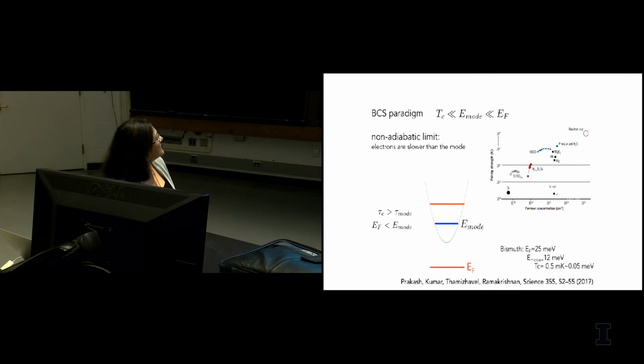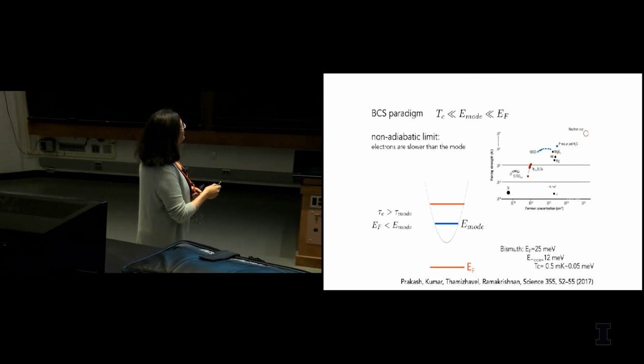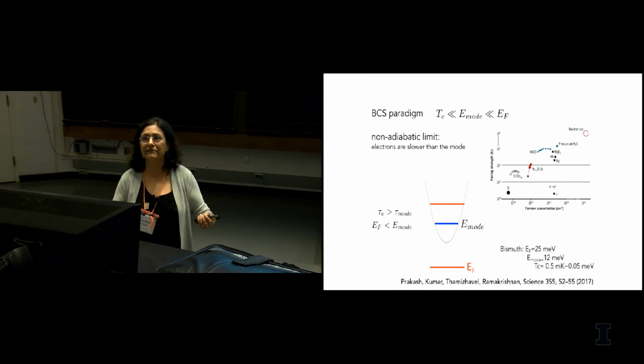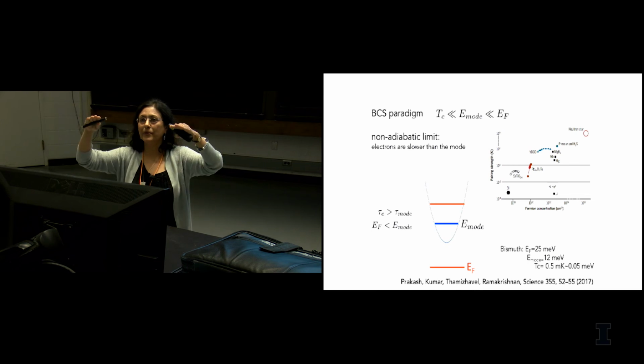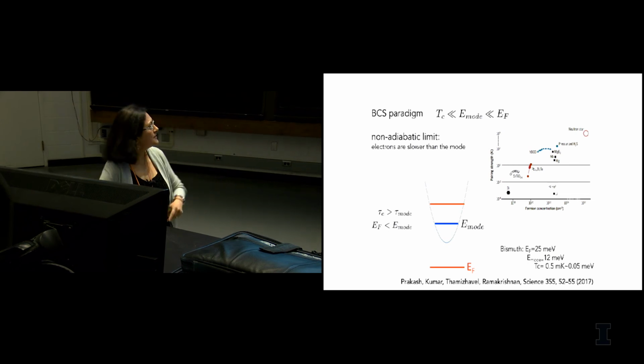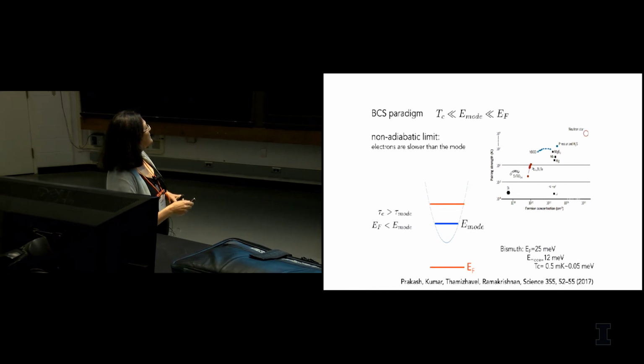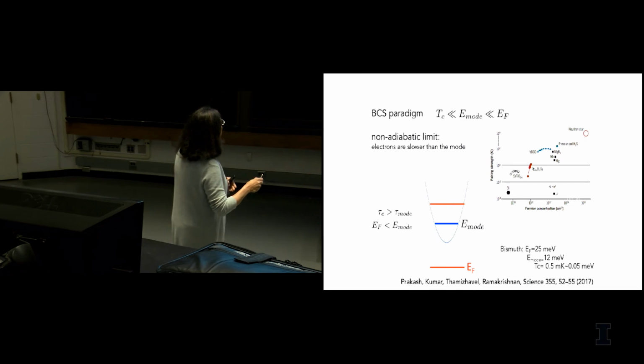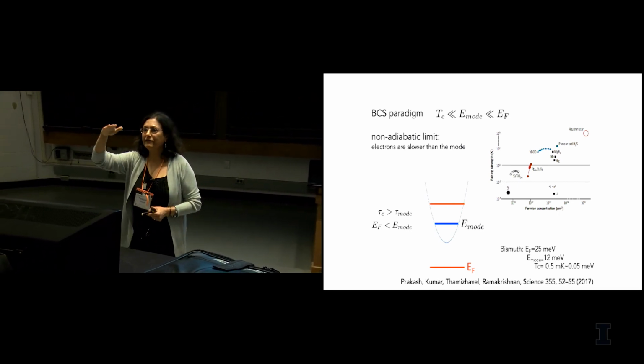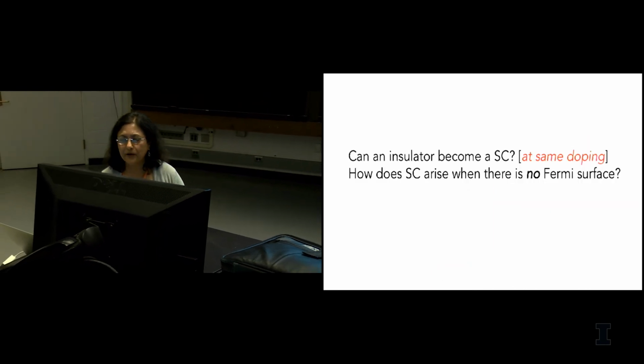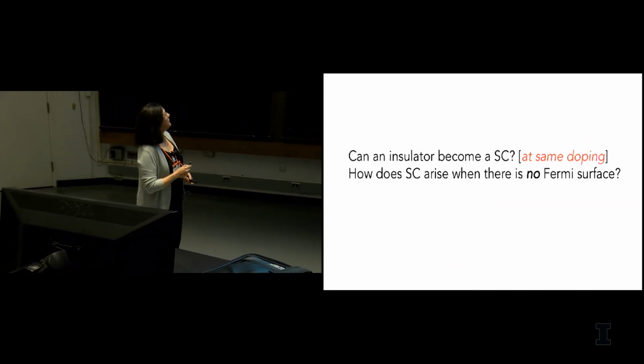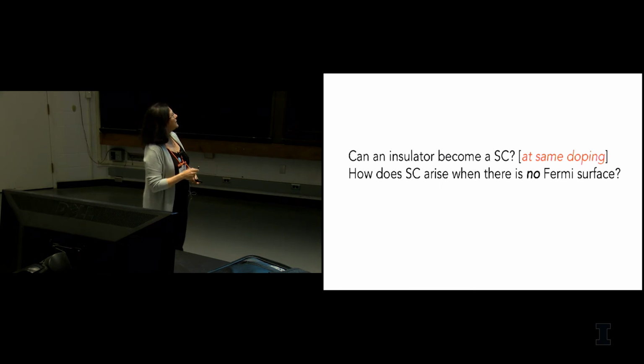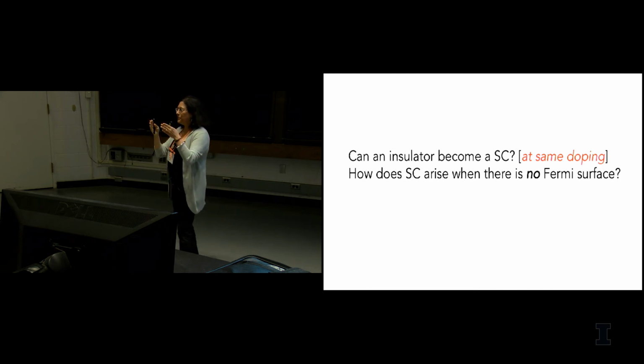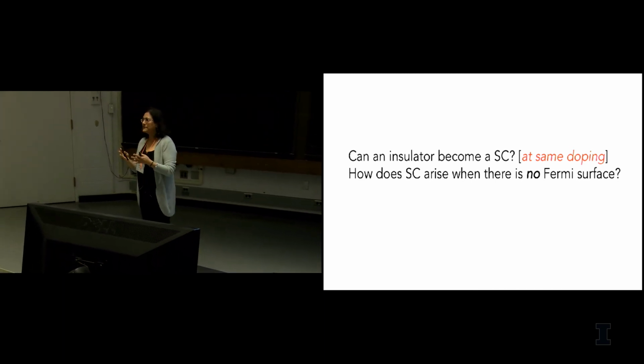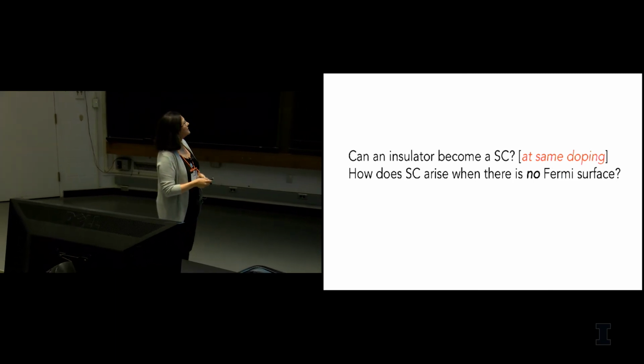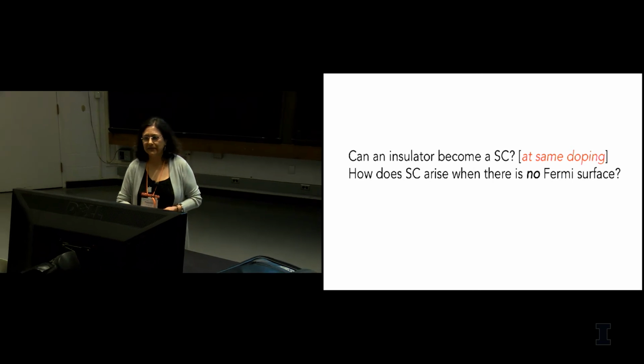The latest example is bismuth, which has essentially one carrier for every 10 to the 5 atoms. So it's a very low carrier system, so EF is really dropping down. In bismuth it's almost coming close, and other low density systems could actually cross this. But we decided to go even further to a regime where EF even drops below the bottom of the band. And the question we asked was, can a band insulator become a superconductor? If you have a system with no Fermi surface, as for example in a band insulator, how would that develop superconductivity?